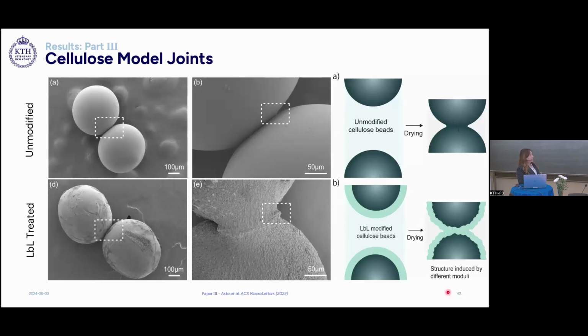What's happening here is basically, after adsorbing 5 bilayers of PAH and HA on the surface, we have an LBL film of around 70 nanometer thick. When this LBL film dries, it will shrink and wrinkle, and therefore will alter the underlying cellulose bead. This means that the cellulose bead will have built-in stresses from the inhomogeneous drying of the two materials. The drying of the LBL treated materials will also cause shrinkage of the contact area, which is much rougher than the untreated materials.